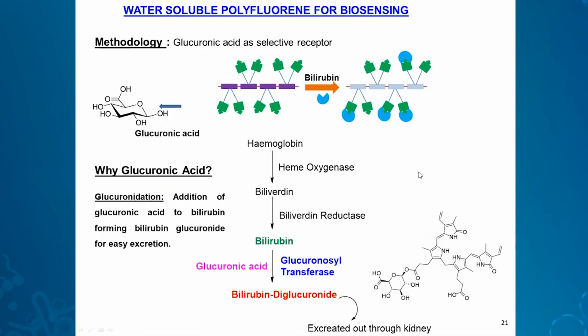Then we wondered if we could do the same in water, because in the blood, the test has to be done in blood serum, so the polymer has to be water soluble. What we realized was, as I showed earlier, glucuronic acid is the molecule which takes away unconjugated bilirubin from our body. It forms glucuronic esters, which makes the bilirubin water soluble, and it is removed from the body. So we thought, why not use glucuronic acid to make polyfluorene water soluble, and at the same time it can also be used as a selective receptor. So two things in one go, if this can be achieved.